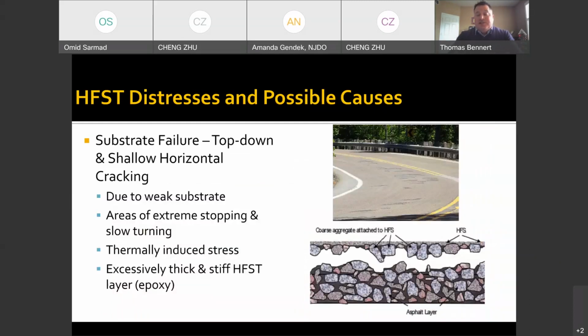These distresses, these shallow distresses, are typically caused from a couple of things. One, we have a weak substrate. The pavement layer below may be prone to some raveling or cracking. It usually occurs in areas of turning or some extreme stopping, so you have some external forces that are being generated. They are also caused by thermal induced stress, and we'll talk about that in a minute. And it can also be caused by excessively thick epoxy.